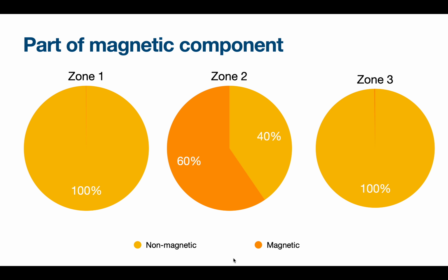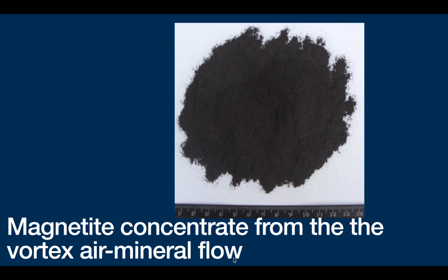Due to it, the percentage of natural and man-made elements with magnetic properties was evaluated. The technology for separation of river alluvium in the vortex air mineral flow is based on the physical properties of the particles. The difference in magnetic properties of the alluvial components provides opportunities for dividing sediments into fractions due to the influence of magnetic fields of varying strengths.